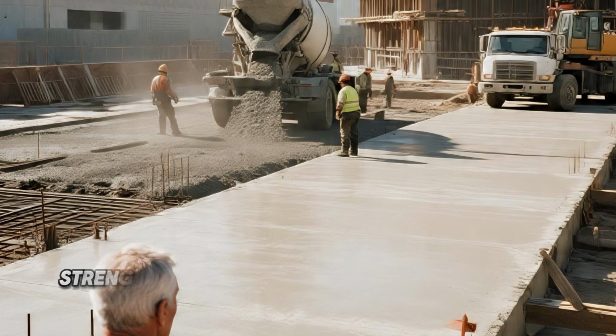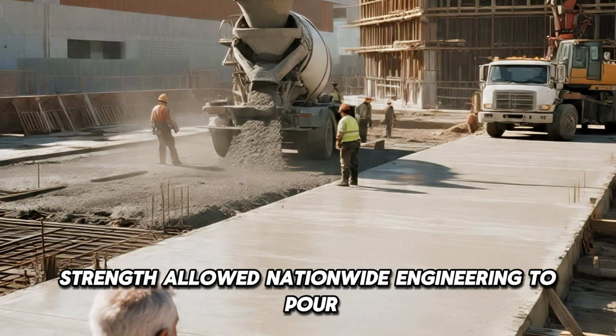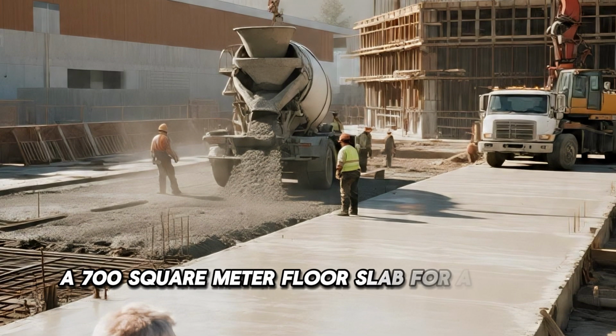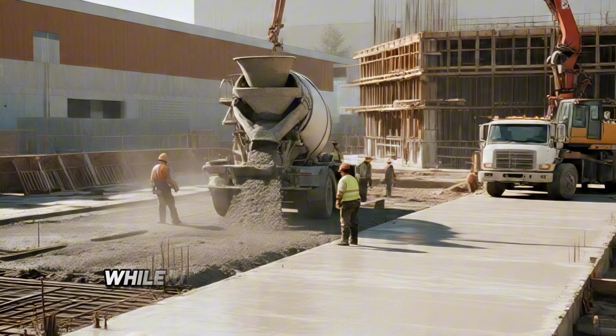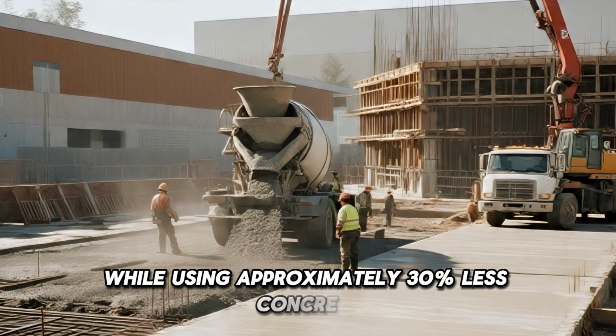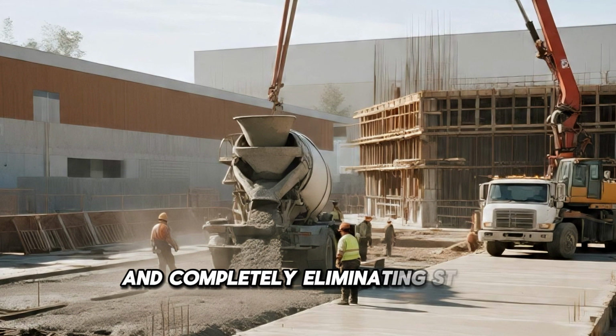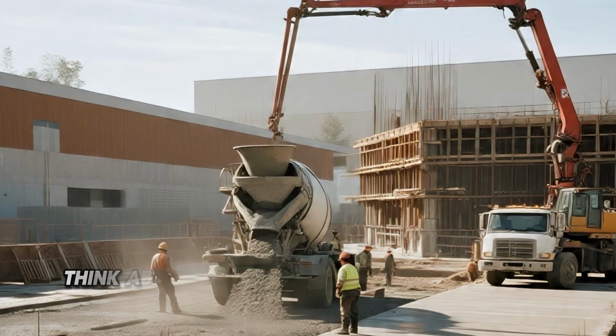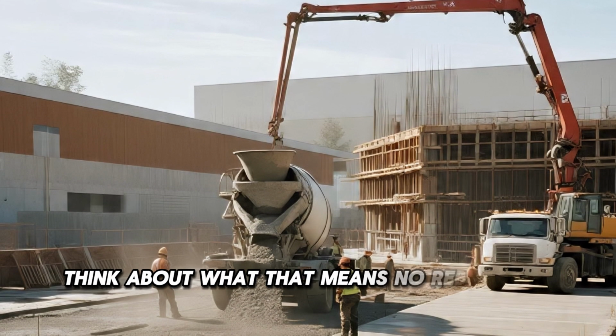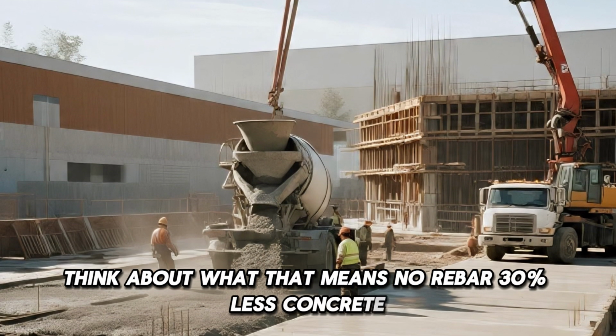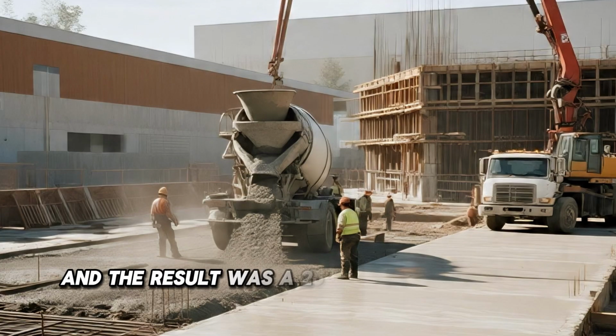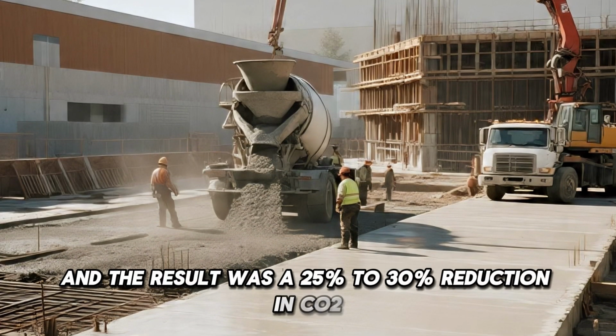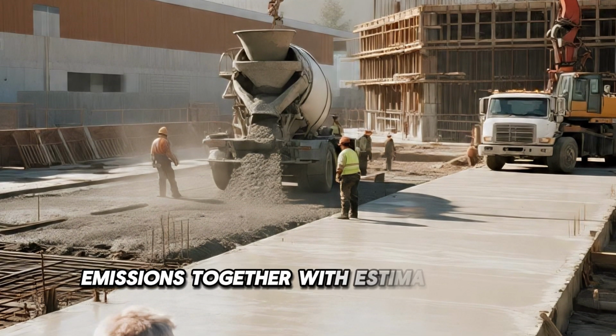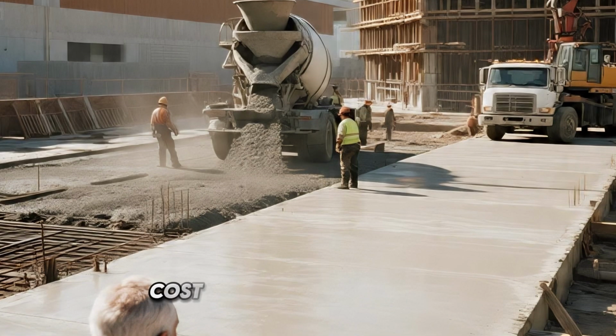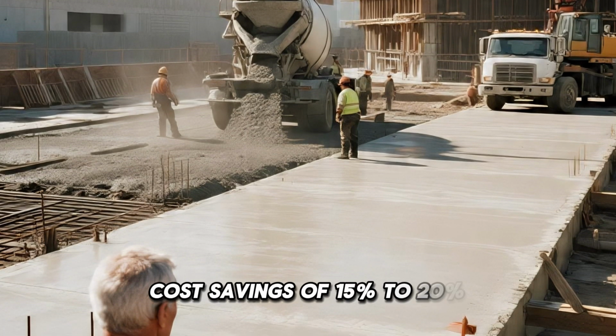That additional strength allowed Nationwide Engineering to pour a 700 square meter floor slab for a gym in Wiltshire while using approximately 30% less concrete and completely eliminating steel reinforcement. Think about what that means. No rebar, 30% less concrete, and the result was a 25% to 30% reduction in CO2 emissions, together with estimated total construction cost savings of 15% to 20%.